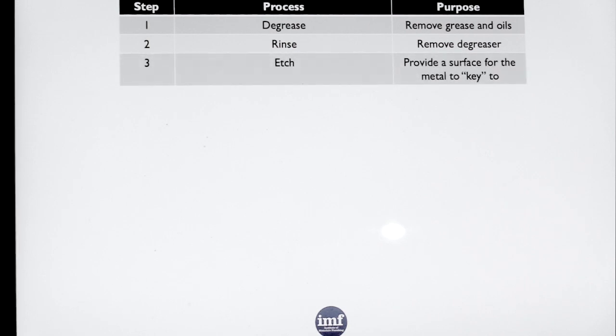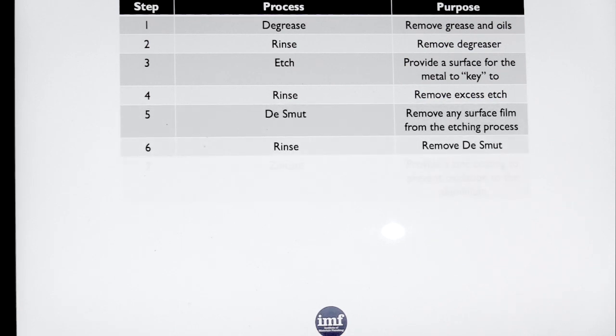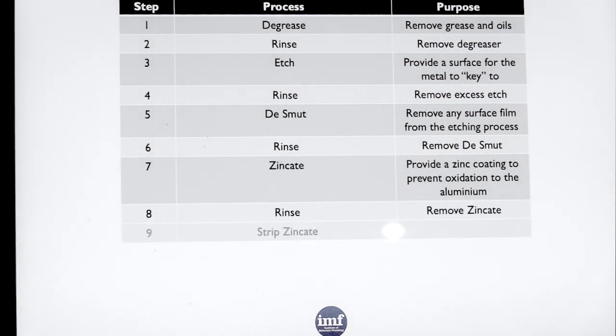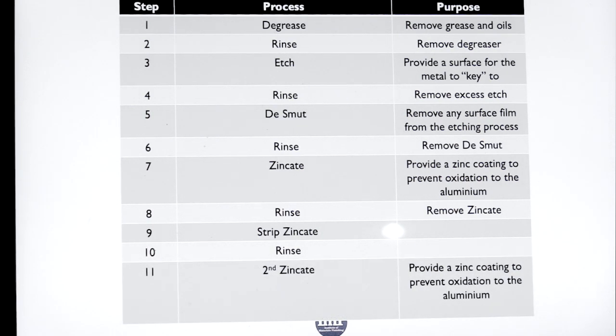Okay, so if we flick through these one by one, this basically is what we've talked about. Degrease, remove grease and oils, rinse, etch, provide a key, rinse, remove the excesses, de-smut if there's any copper or silica, rinse, zincate it, rinse, strip the zincate, zincate it, rinse it again, zincate it again, and then electroplate. That basically is the standard process used for plating aluminium, and it's been like that since time immemorial. Nobody's produced another way of doing it. It works extremely well. It's very simple. If you do it right, you can get 100% success out of it, and you get some very good plating results. It does have high strength adhesion, especially by doing the double zincate process here.